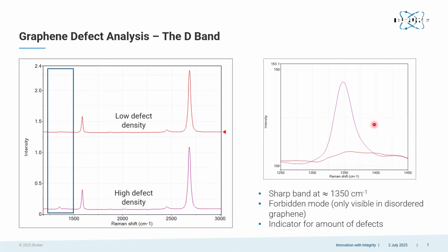You can also do here the ratiometric approach and do the G to D ratio to have a more robust analysis method to compensate for baseline or any other effects that might come during your measurements at different positions in your sample.